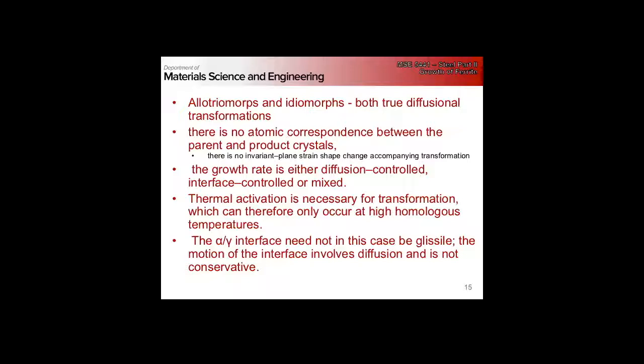Here we're nucleating these primarily heterogeneously, but this is still only going to occur at high homologous temperatures, near our eutectoid temperature. If we get too low, we're going to grow Widmanstatten. If we get even lower, it's going to be bainite. If we get even lower in temperature, it's going to be martensite.